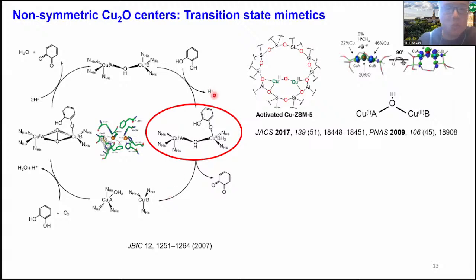What we came to notice in a lot of these works is that although the resting structure of these compounds usually involves 2 copper and a bridging oxygen species sitting in a symmetric structure, the active site or reactive intermediate or transition state usually features a highly anisotropic structure. Looking at this one, right? This copper has coordination number 4, this other copper coordination number 5. So this seems to imply that such breaking of symmetry induces certain kind of enhanced reactivity.